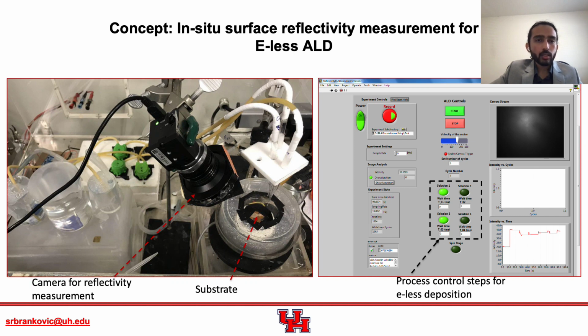So with these factors in mind, we have developed this customized setup at University of Houston, which is based on surface reflectivity of the sample during deposition. So here is a CCD camera and this is the light source. So we illuminate the sample as shown here with a light source and then we capture reflectivity from the surface. And this LabVIEW code designed at the University of Houston allows us to control electroless deposition processes as well as we can see reflectivity from the sample here in this image. So with help of this tool, we can evaluate surface reflectivity changes during electroless deposition process.